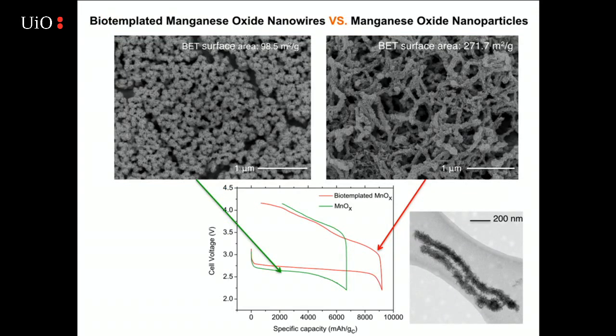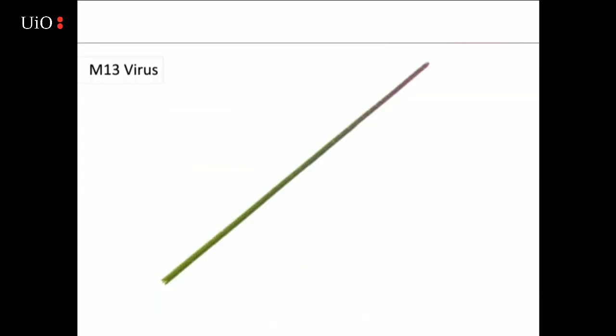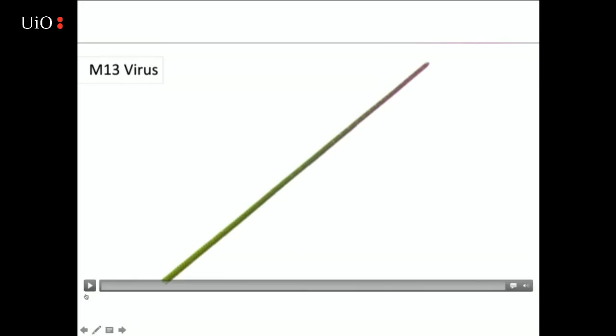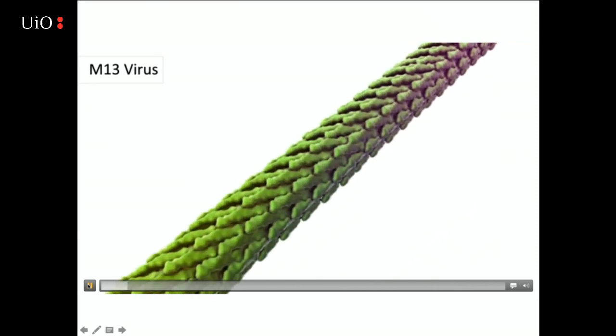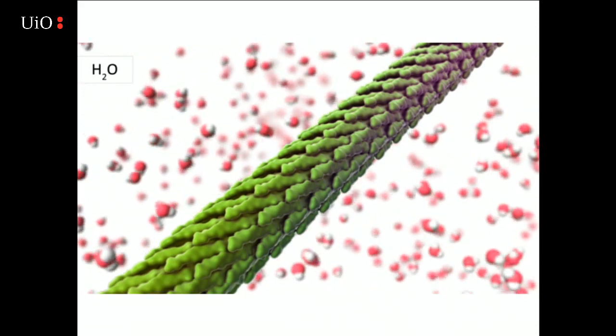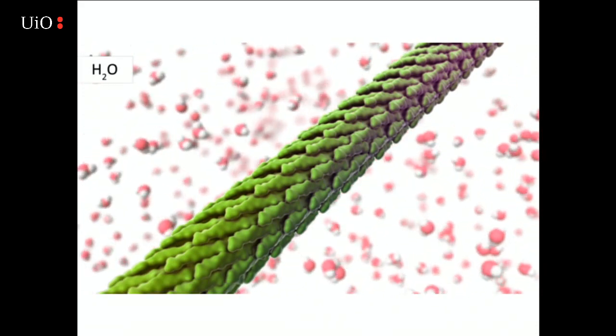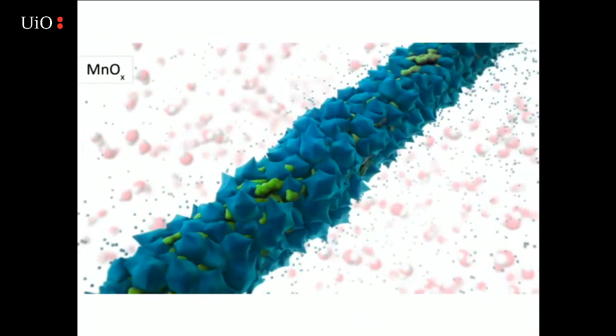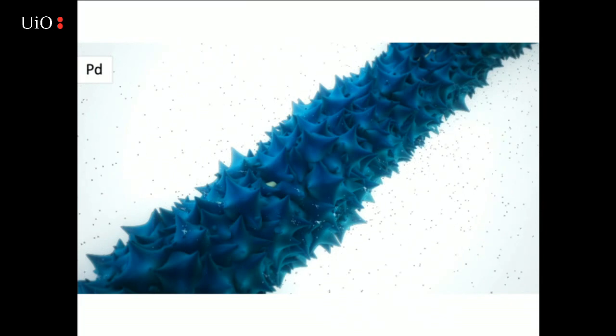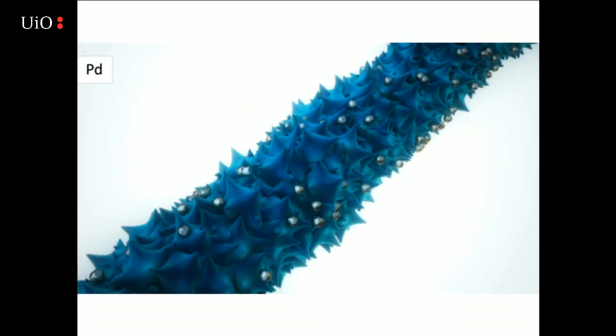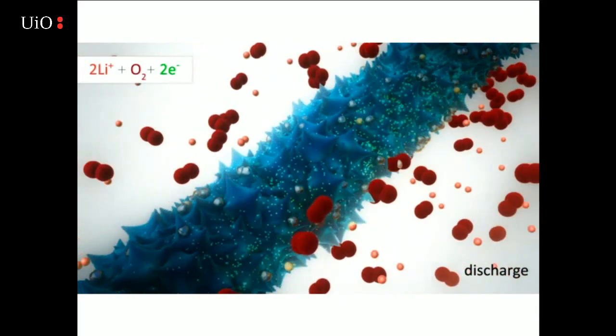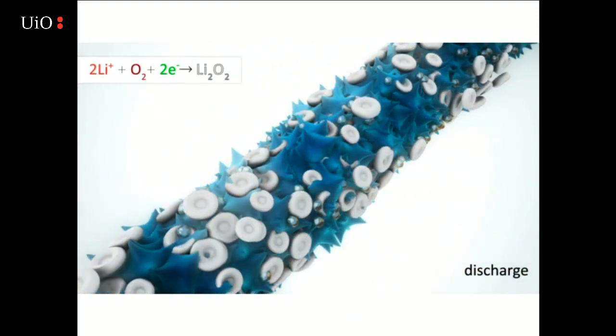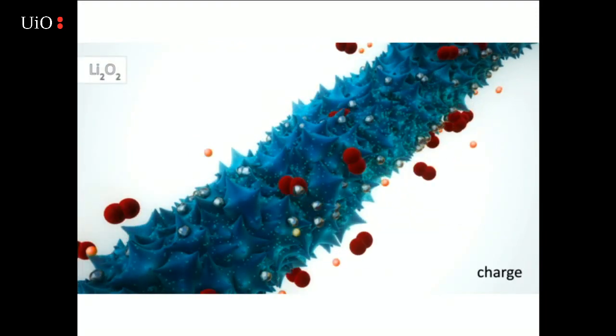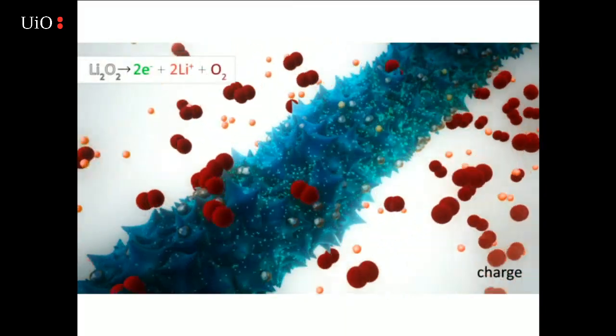This is a cartoon my students made of what the idea is that you have a virus that's in water, it's in solution. You have modification of each of these proteins that allows for the nucleation of these manganese oxide materials. You have manganese, you grow these spiky kinds of structures. You add in a little bit of palladium to this, and then the reaction you have is lithium plus oxygen plus 2 electrons, forming the lithium peroxide. That's reversible. So that's a single wire. Now you make billions of these wires.